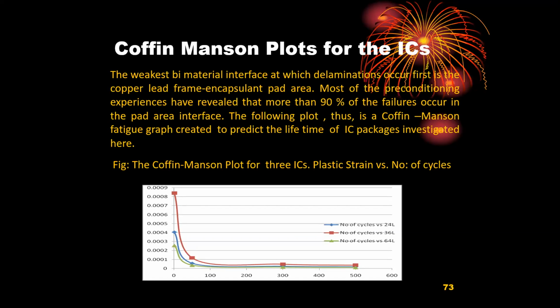But what happens is that when plastic strain is removed at elevated temperatures, each time you fatigue cycle from room temperature to the elevated temperature or the maximum operating temperature, because of cycling, the moisture susceptibility increases. When moisture susceptibility occurs, it takes in a bit of moisture and becomes a little more plastic again. So what I suspect is that Coffin-Manson may not be everything. We have to consider plasticization because of repeated cycling and then moisture susceptibilities in the long run. And we have to check what would be the swing in plastic strain with respect to cycling.